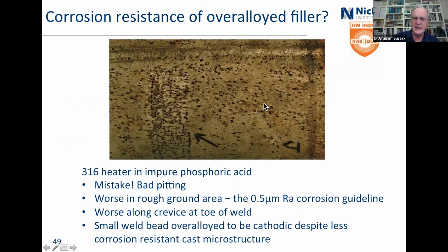This is a piece of 316. It was a piece that was used as a heater in some impure phosphoric acid. And you can see very bad corrosion here. This is the sort of 0.5 micrometer corrosion guideline, pitted all over the place. Where it isn't pitted is along this weld. Why? Because the weld is over-alloyed, and that's over-alloyed so that you don't worry about losing chromium and getting a different potential. And basically, you're trying to make sure that the smallest thing there has got the highest potential and therefore is the most resistant to corrosion. And yes, I can see some pits along the bottom here, but that's a crevice basically at the toe of the weld.